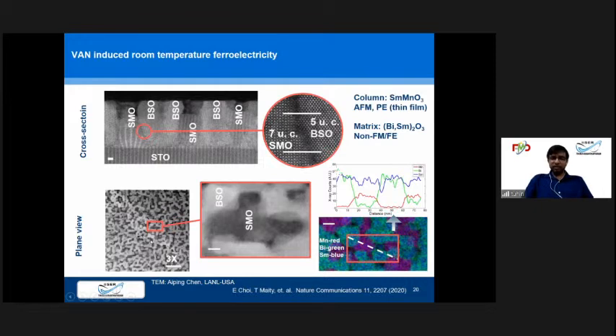So as we deposit the material, this is the top view you can see, the TEM image. This is samarium manganese oxide pillars, and it is surrounded by this matrix of samarium oxide. And as you can see, this is called element mapping. The red is manganese and the green is the other element; where they mix, it becomes violet. So the manganese is nowhere here, so they are well separated. That means by this process we can create a well separated double phase or double material system.